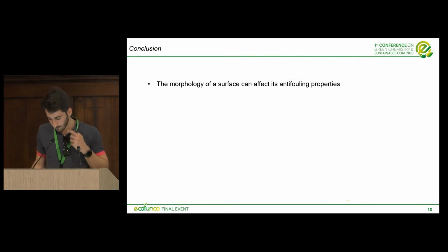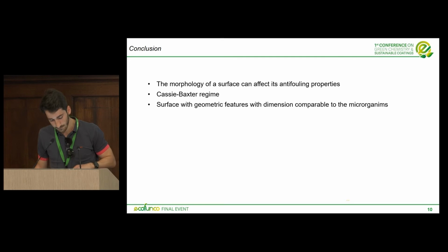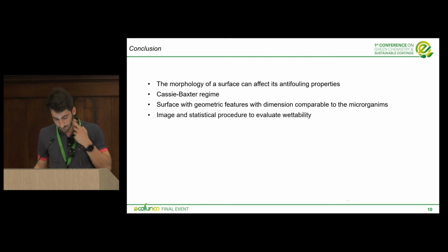To conclude, we have seen how tuning the morphology of the surface can affect its antifouling properties. Precisely, by fabricating a multi-layer fibrous coating that raised the wettability of the surface to a hydrophobic level, we have observed that the fact that we have entered the Cassie-Baxter regime, so a super-hydrophobic regime, and the fact that the surface has geometrical features with dimensions comparable to the microorganisms, affect substantially the antifouling properties of the surface. And these observations can be used in the future to tailor or design new surfaces. Furthermore, we have developed an image and statistical procedure to evaluate the porosity and then the future wettability of electrospun meshes.